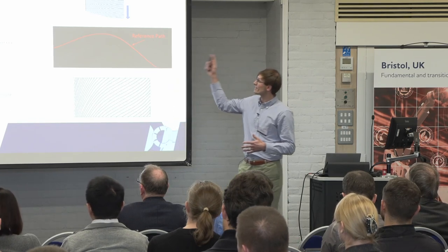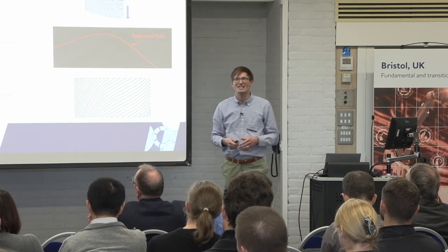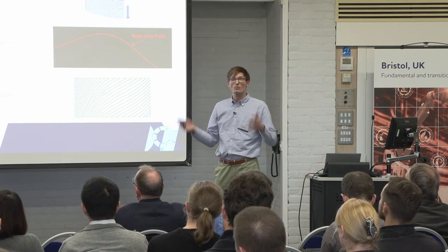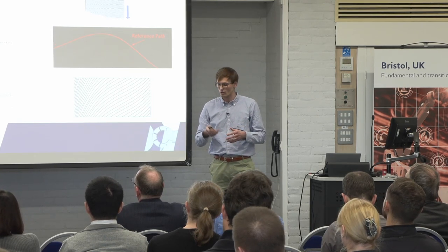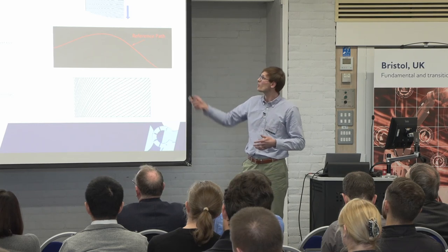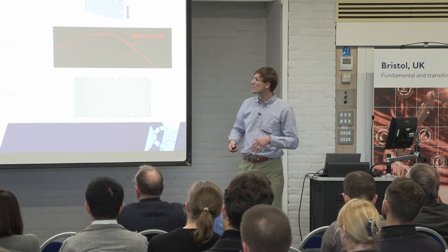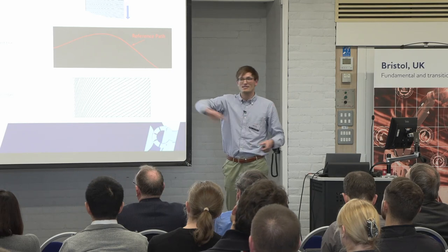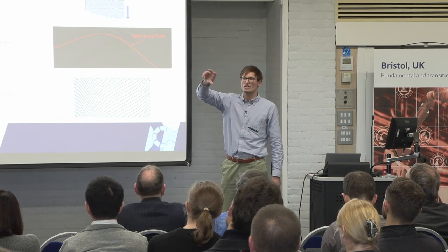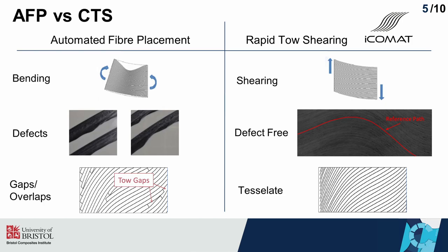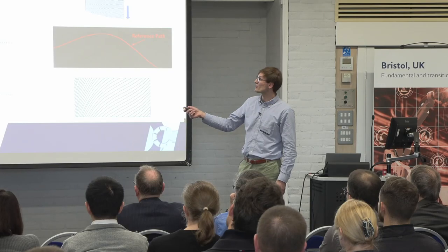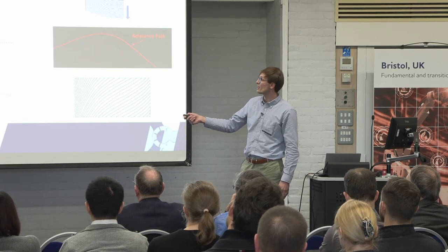Now, just as an example of the two different manufacturing techniques that exist: in the beginning, when people were looking at these variable angle tow composites, the only thing that was really possible was to use an automated fiber placement machine, where you take a classic AFP process and all you do is rotate the head as the head is traversing across a plane. That essentially puts the tow under bending and allows it to be steered. But the issue with that is that it really limits the steering radii that you can achieve, because at some point, the inside of the tow is being placed into compression, and you get these defects.